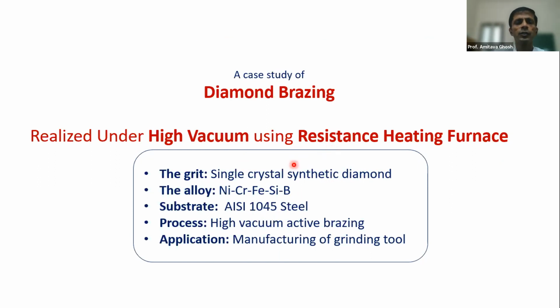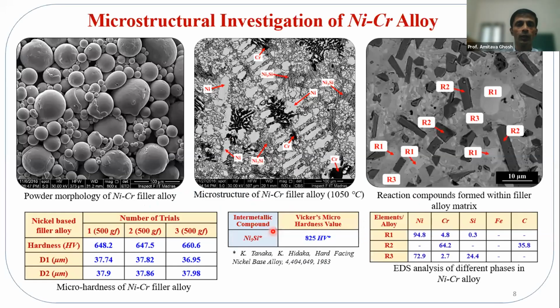So here in this case study, we choose a grit, which is single crystal synthetic diamond. The alloy is a nickel chromium alloy, which is quite hard when it becomes solidified. Substrate is just a medium carbon steel, and the process is high vacuum active brazing. This high vacuum active brazing, I'm just coming to that a little more in depth. After that, we'll try to see how the laser can be beneficial. And then application is basically manufacturing of the grinding tool.